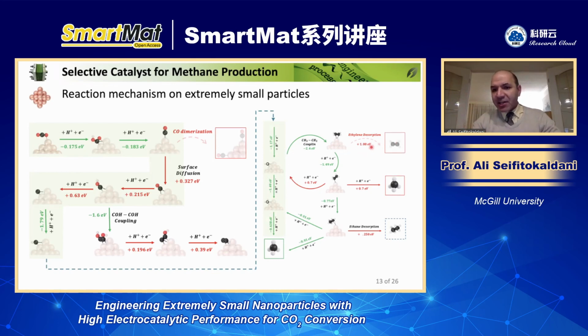So the barrier to leave the surface is too much, like 1 electron volt. But then on the other side, if we keep further protonating the ethylene, the energy is not uphill, it's rather downhill, and you can easily expect this step. So once further protonation happens, again, the next step is still too difficult to produce methane, to leave the methane or get back to this one.